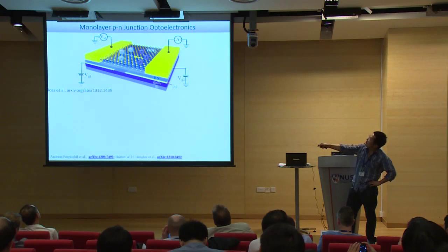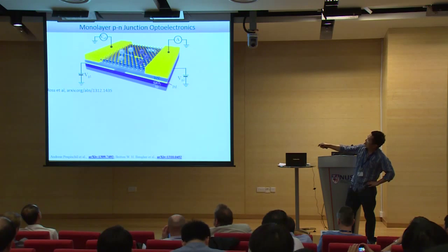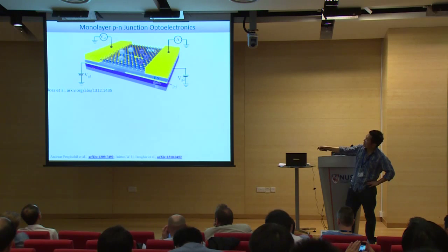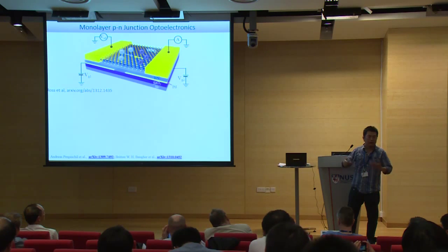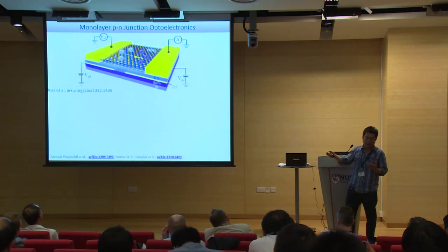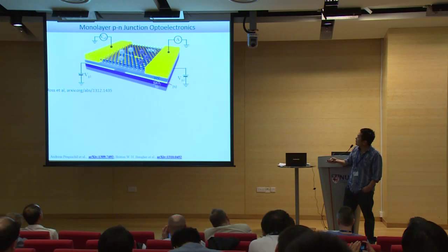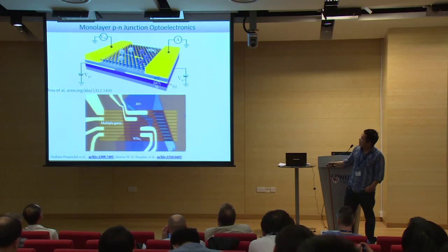The idea we use here is that you can see the metal contacts connecting these tungsten selenide actually sitting on top of the bottom gates. So we're hoping to use a little bit of screening effects to erase these Schottky barrier effects, and again, we can create a good contact. So this idea works, but not perfect. And this is the image of the device we have.